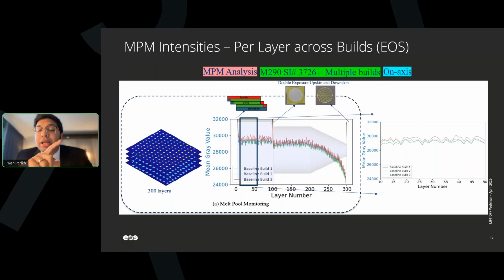So of course, the overall trend seems to be similar. Of course, you see the spike at 100 layers because of the change in cross section. But again, the 10 to 50 layers were investigated, and you see the red, blue, and green lines not superimposing on top of each other. That's the whole point of running the nominal jobs. Go to the next one, please.